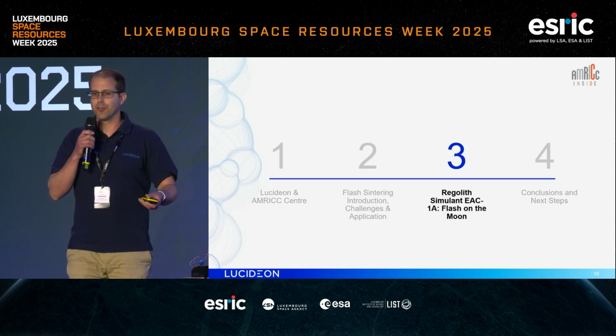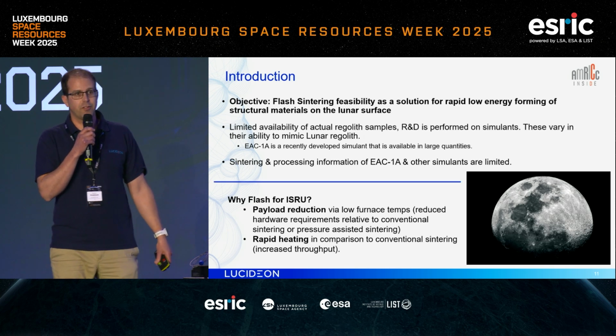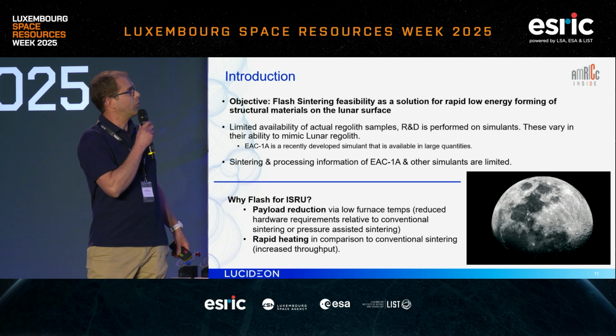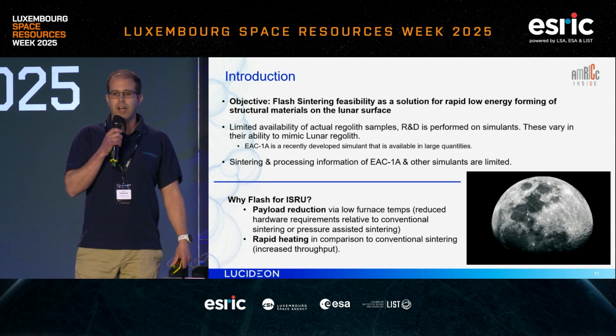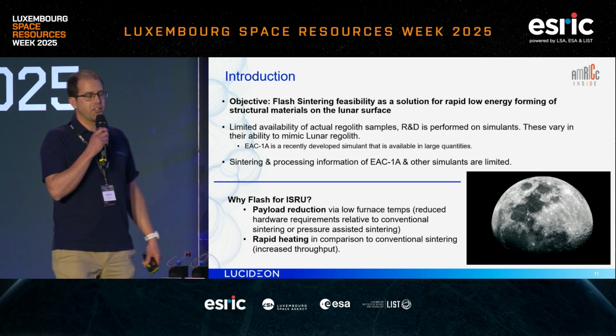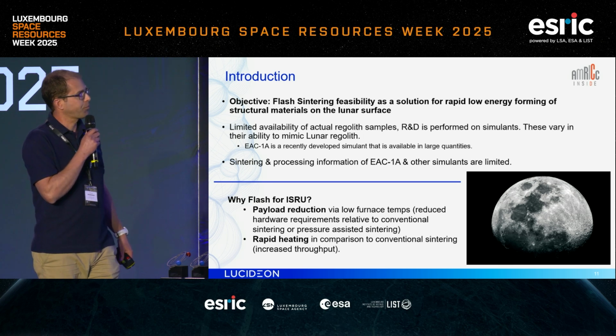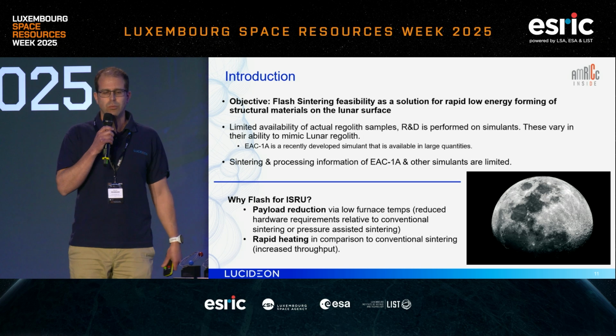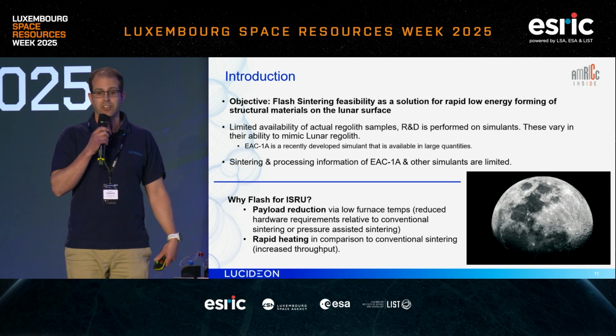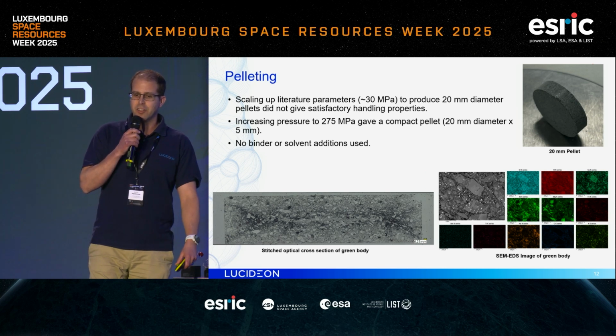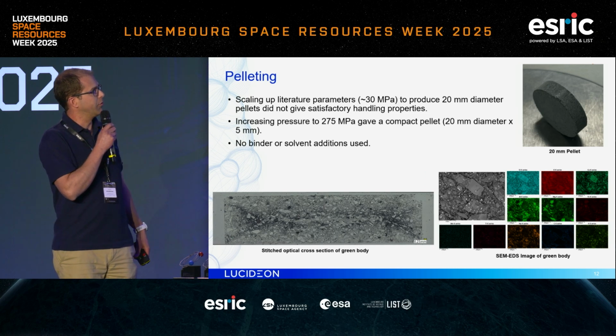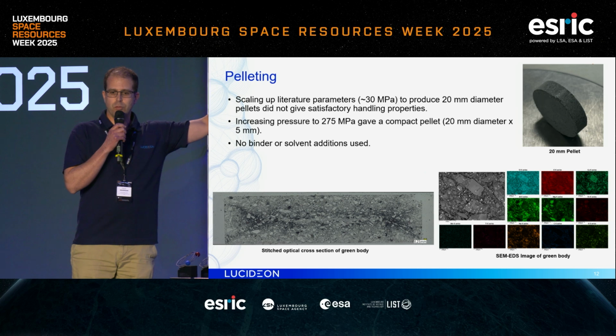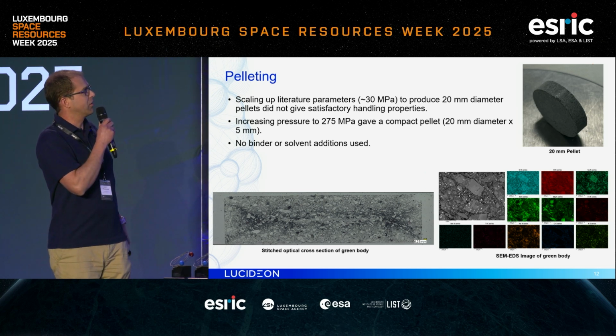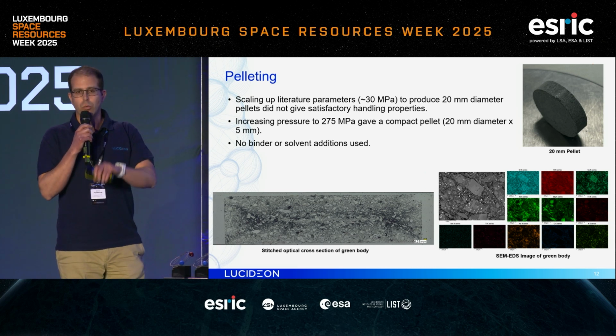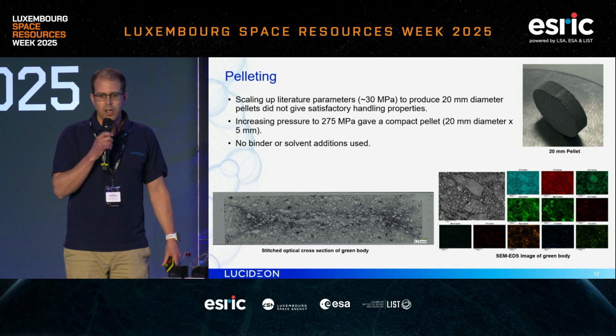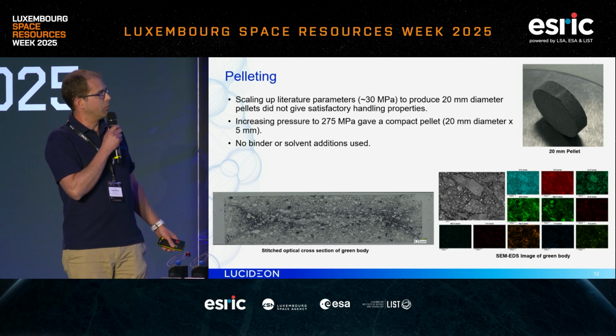So onwards then to how all this is applied to our regolith simulant. This project itself, and thanks to ESA for the funding for this work, aimed to show a feasibility study of flash sintering as a low energy technique for sintering simulant, and we used EAC-1A in this particular study. And of course that was the low energy part, with the intention of reducing payload and efficient sintering and rapid heating processes. Pelleting first, though, it's an important part of it, and looking at the homogeneity and the pressing of your regolith simulant. Looking around some of the posters and things, we've got similar results in an independent study, which is fantastic. So we were pressing to 275 megapascals, and that gave quite a nice pellet. All the work you see is on 20 mil pellets, about 5 mil thick. And there's a little cross-section of the green body there that we formed.